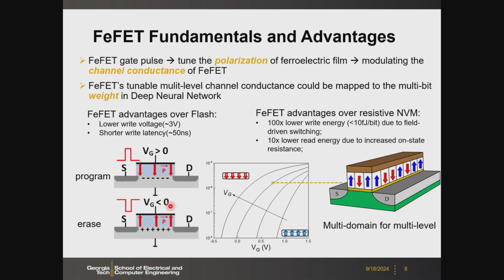And if you reverse the voltage polarity, let's say polarize all the dipoles up with a negative voltage, then the channel could be in accumulation. Then the threshold voltage will be higher, like this. Of course, you can partially polarize by using some intermediate voltage. Let's say some dipoles up and some dipoles down, then you can get those intermediate states. We can use this as a mechanism to map multi-level weights into multi-level channel conductance.